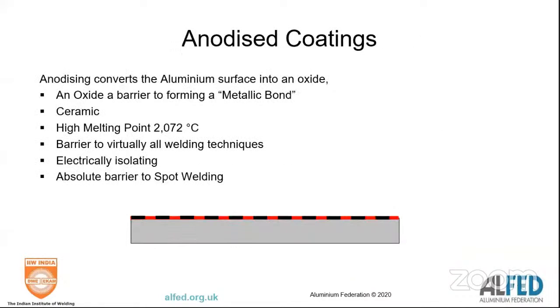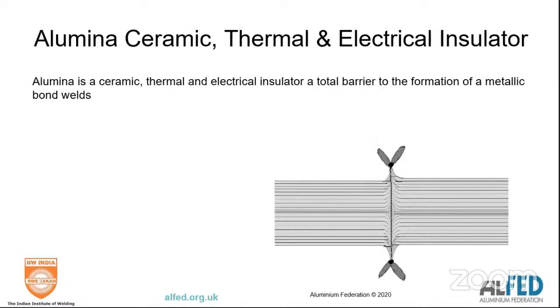You're going to come across anodized coatings. In essence, in anodized coatings, we electrically and deliberately oxidize the surface of aluminium to produce an alumina coating on it. If you've got an anodized coating, you will never, ever be able to weld it. It's an absolute total barrier. So, alumina: thermal and electrical insulator, total barrier.